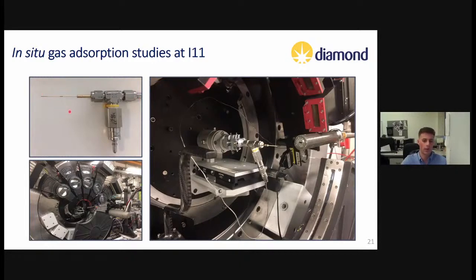The way this works is that we can pack our powdered sample in a quartz capillary and seal it inside this Swagelok component, which we refer to as a gas cell. We can attach that gas cell onto a motorized stage, connect it up to a gas inlet, and although we're not able to continuously rotate our sample, we are able to rock this stage to ensure good averaging. I11 is set up so that there are two different detectors, a PSD and a MAC detector, and we're also able to control the temperature through the use of a cryostream.